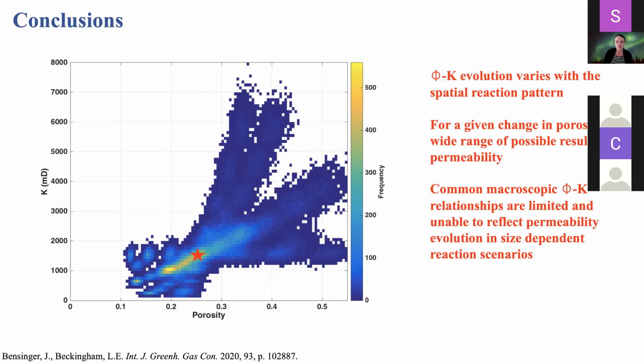So from this work, we saw that the evolution of porosity and permeability depends on the spatial reaction pattern of mineral dissolution and precipitation reactions at the pore scale. And that for a given change in porosity, there's really a wide potential resulting permeability. And that makes using these macroscopic porosity permeability relationships really challenging because we're not able to reflect what's happening at the pore scale. And this was particularly true when the reactions were related to or controlled by the size of pores and pore throats.